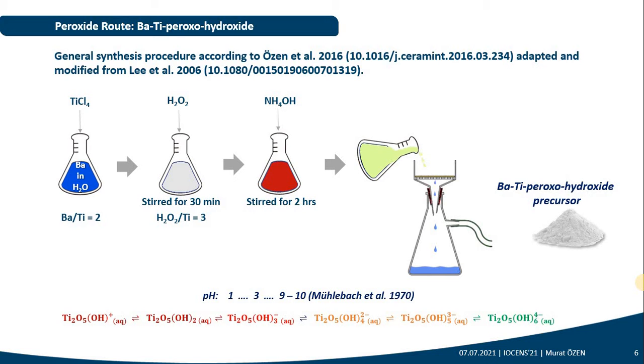Titanium tetrachloride is added to a barium aqueous solution with barium-titanium ratio of 2. Afterwards, hydrogen peroxide is added to this barium and titanium aqueous solution. The peroxide-titanium ratio was kept at 3. The solution was stirred for about 30 minutes. Afterwards, the solution was treated with ammonium hydroxide to about pH of 10, and the solution was then stirred for another 2 hours. After 2 hours, the solution was filtered through a Buchner filter, and the final barium-titanium-peroxo-hydroxide precursor material was obtained.